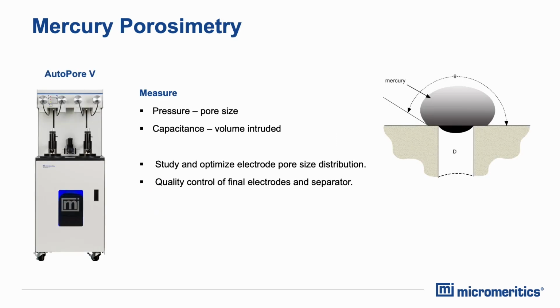Let's now look at mercury porosimetry. As I already mentioned, this is also a technique where we can calculate pore size distributions, pore volume, and even also surface areas. And like gas adsorption, mercury intrusion takes advantage of the relationship between pressure and pore size. But in this case, we work with much higher pressures, up to 400 megapascal. And the higher the pressure, the smaller the size of pore into which mercury can be intruded.